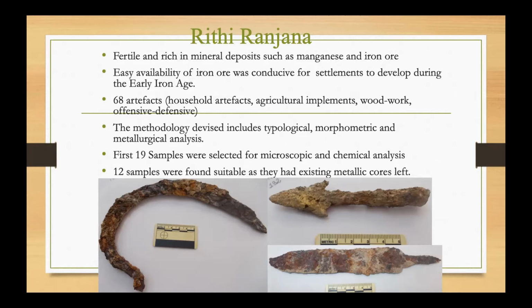And the problem is that once I selected 19 samples and got them back to the lab, when I started preparing the samples, only 12 samples were found suitable. Because to do any microscopic study, we need a metallic core which is existent. But in half of the samples, it looks intact from outside, but the encrustation and the corrosion has infiltrated so far that it is just rust, which crumbles in your hand once you cut. Or it is so rusted that it is absolutely porous and we do not have any metallic core left.